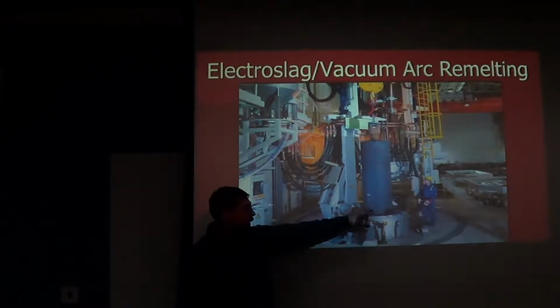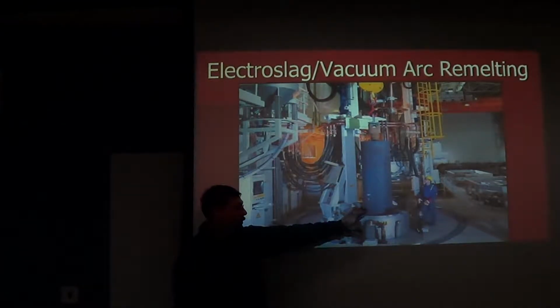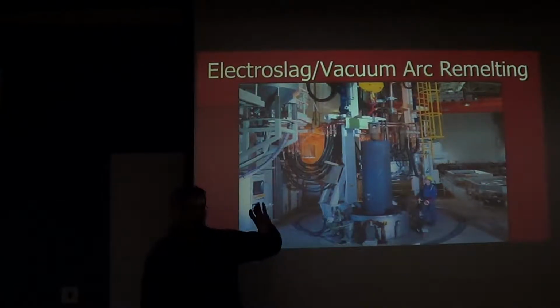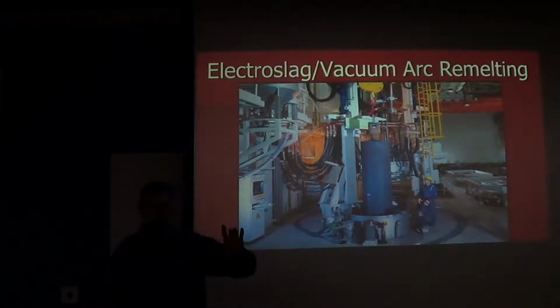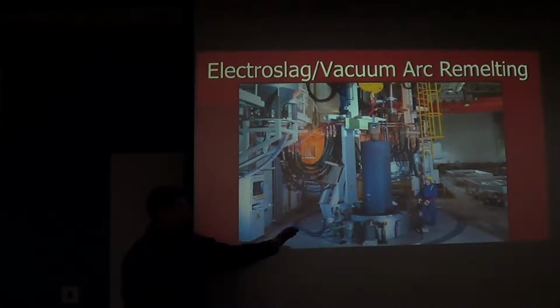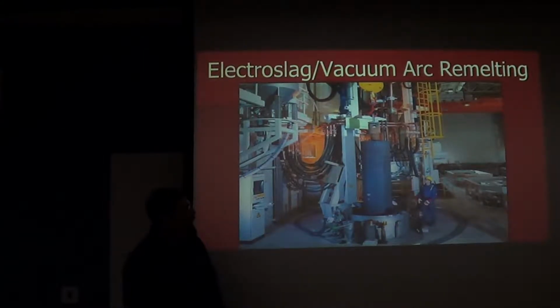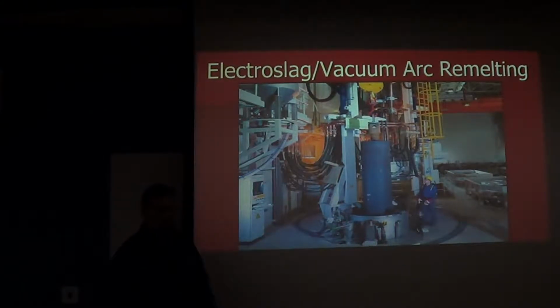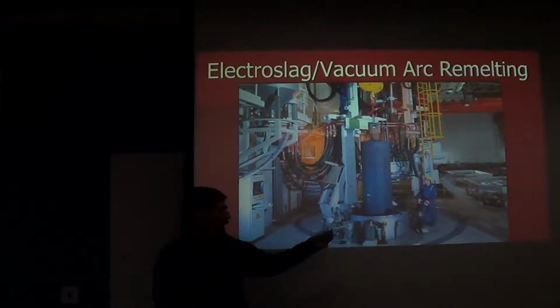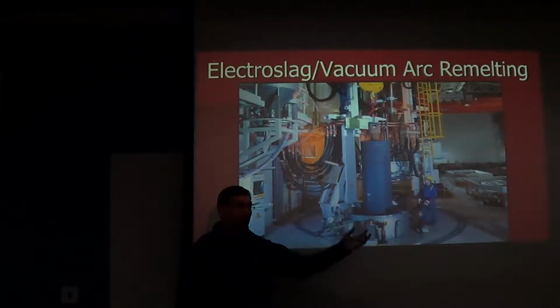So you melt and you solidify, and you are only ever left with a really small amount of liquid metal at any one time. This takes place over, an ingot that size might take a day, maybe 24 hours, 30 hours to go through this process. What's happening is the metal is melting kind of drop by drop off the bottom of the ingot.